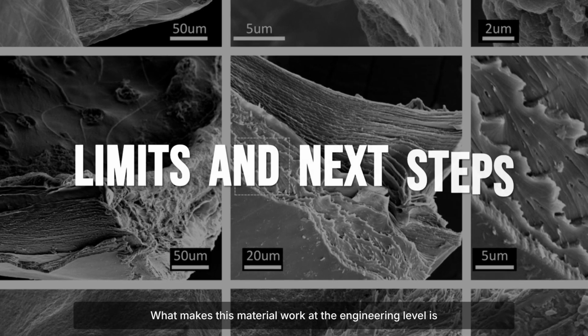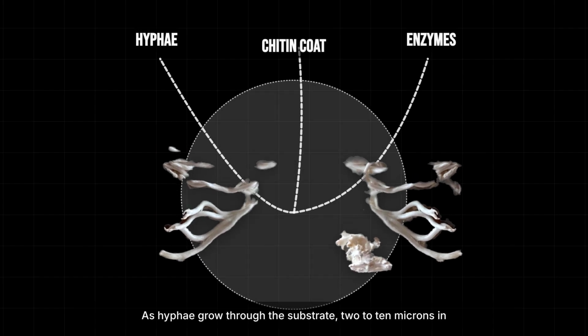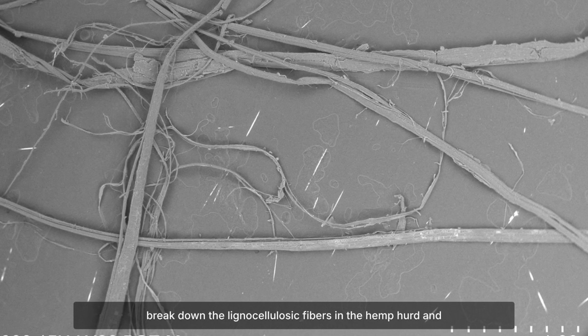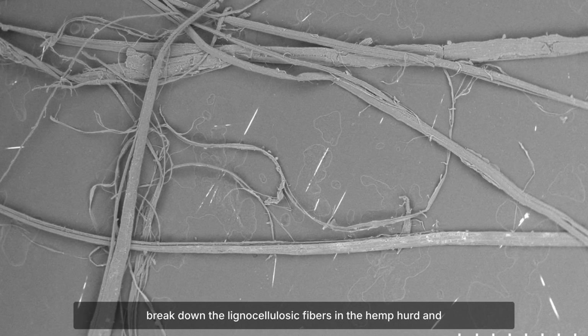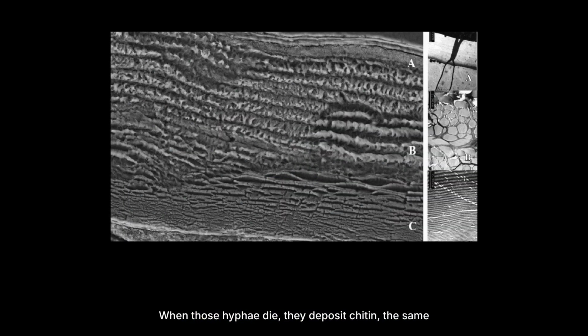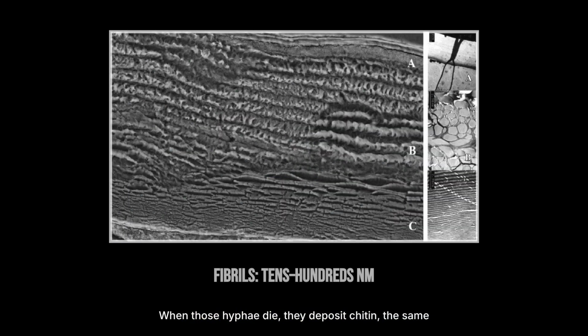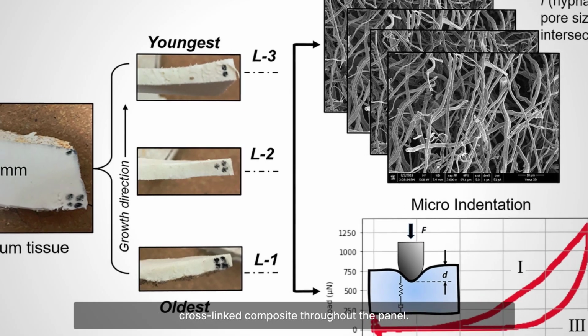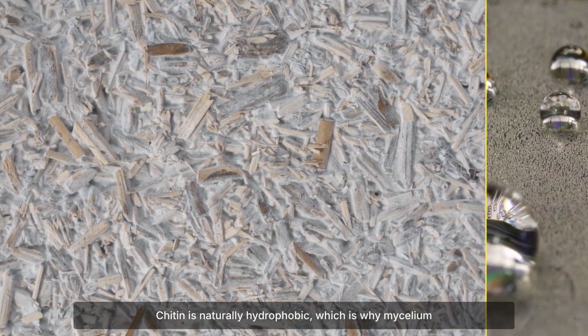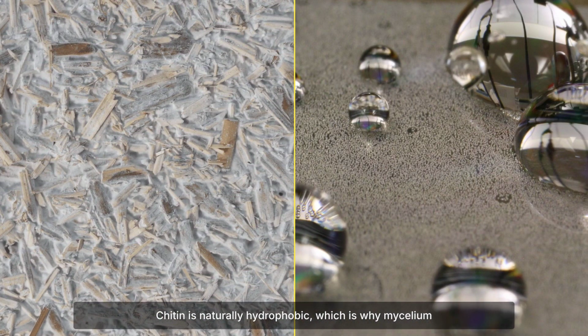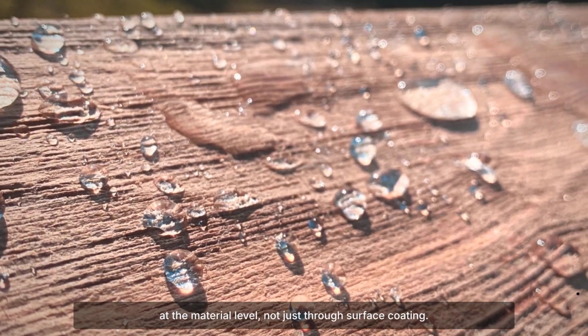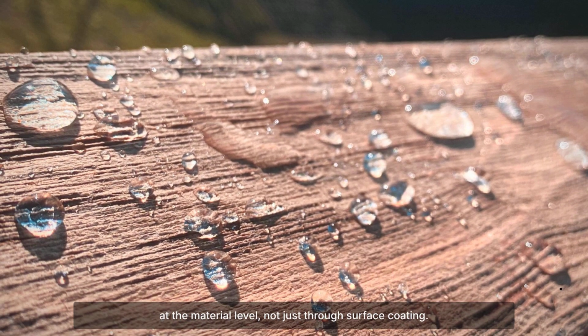What makes this material work at the engineering level is chitin. As hyphae grow through the substrate, 2 to 10 microns in diameter, thinner than a human hair, they enzymatically break down the lignocellulosic fibers in the hemp hurd and thread physically through the matrix. When those hyphae die, they deposit chitin, the same structural polymer that makes crustacean shells rigid, as a cross-linked composite throughout the panel. Chitin is naturally hydrophobic, which is why Mycelium panels resist moisture absorption better than untreated wood at the material level, not just through surface coating.